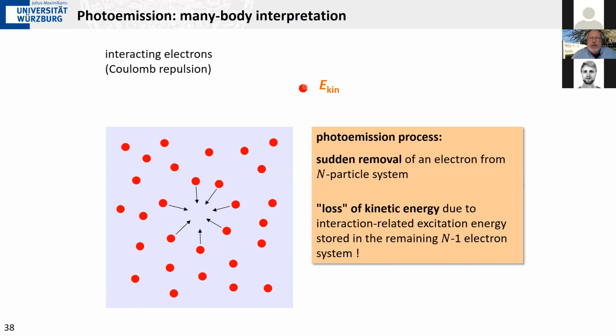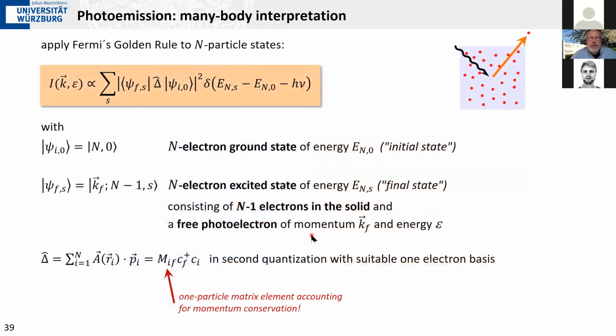Certainly, our photoelectron knows about the excitation energy of the state here, because the total energy has to be conserved. And so the photoelectron kinetic energy contains information about the excitation state of the remaining n-1 electrons. And we can treat this again with Fermi's golden rule, but now we have to use n-particle states rather than just one-particle Bloch states.